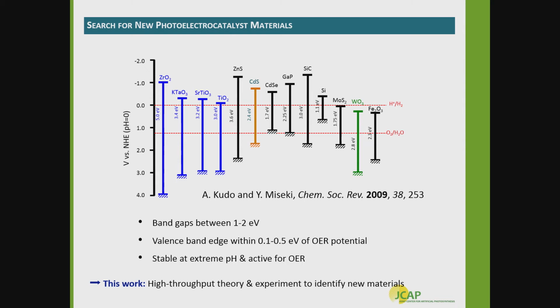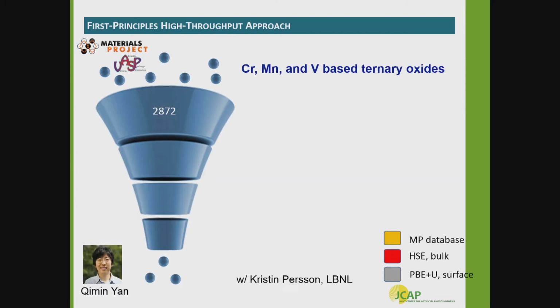And of course, in seeking this holy grail for photoelectrochemical solar fuels generation, we seek semiconductors that have band gaps between 1 and 2 electron volts, so they're broadly absorbing the solar spectrum, and valence and conduction bands that straddle the water oxidation and water reduction levels. So we know about many of the choices that are available to us that have these characteristics, and in general we don't have a large portfolio of ideal candidates here. We have many that are stable under oxidation and reduction conditions, and have aligned band edges but have band gaps that are often too wide, or others that don't have the proper band alignments.